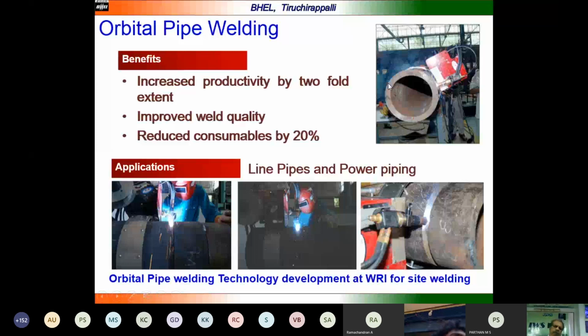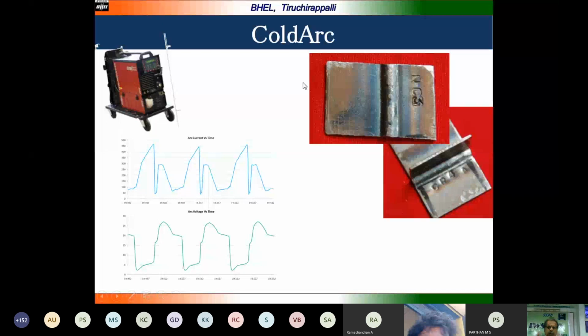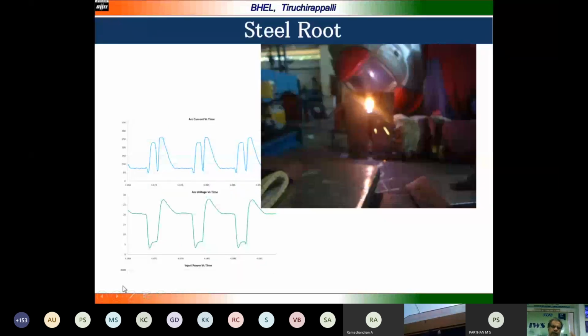The cold arc was again developed by EWM. Similarly, it's a modified waveform welding process which can be used for application on thin sheets, and only the power source has a variation, with small changes in the current and voltage waveform as we are seeing here. The application is low heat input for welding of thin sheets and root pass welding. The waveform recorded in the analysis at Hanover by one of my colleagues, Shanta Kumari, is shown here.